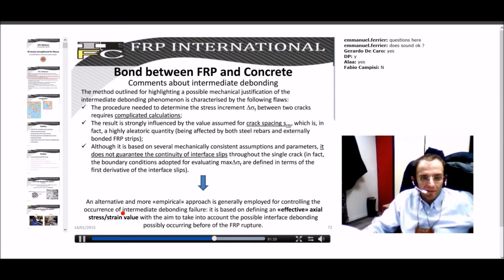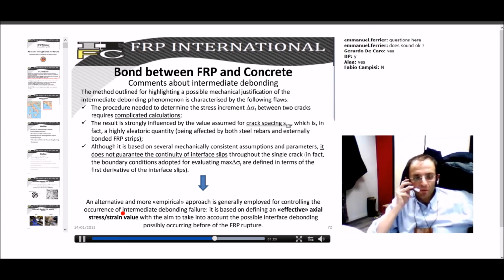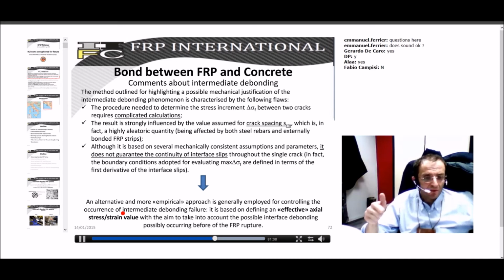So, as you see, I've tried to justify from the mechanical standpoint the occurrence of both the end debonding, which is quite straightforward, and also the intermediate crack-induced debonding, which is a little bit more complicated, as you see, because one has to decide what is the actual distance between cracks. So one has to evaluate the axial stresses sigma in all sections, and then to evaluate the stress in terms of delta sigma and the corresponding strength, and compare delta sigma with the maximum delta sigma to assess whether debonding occurs or not.